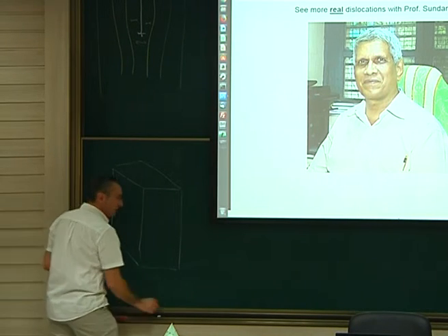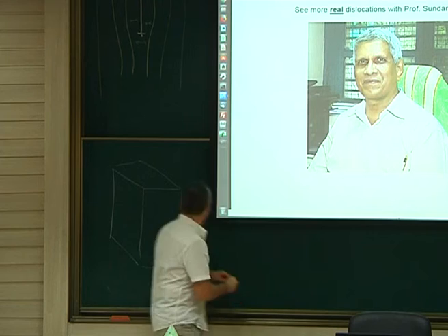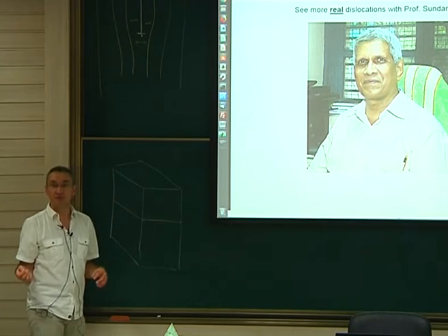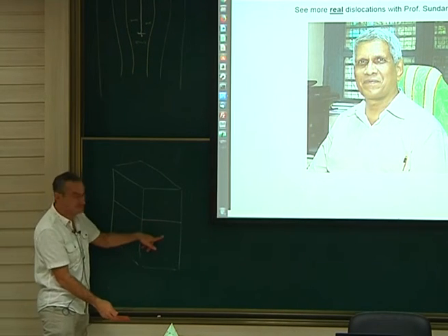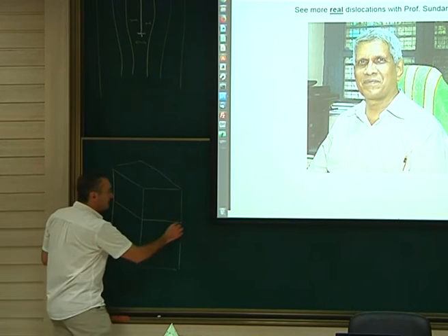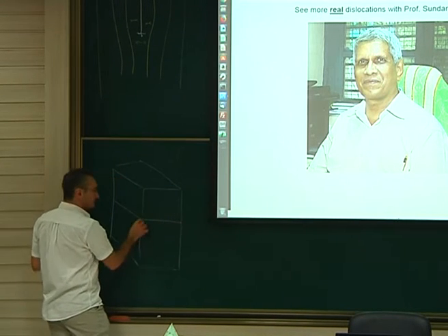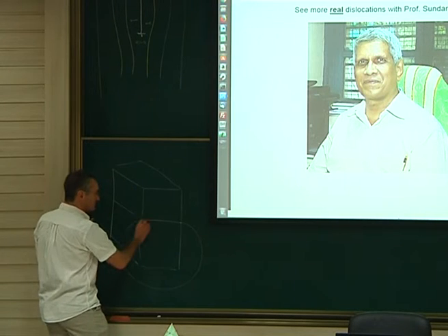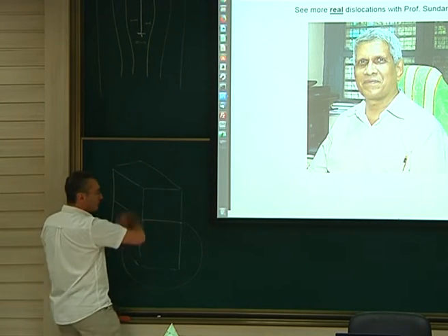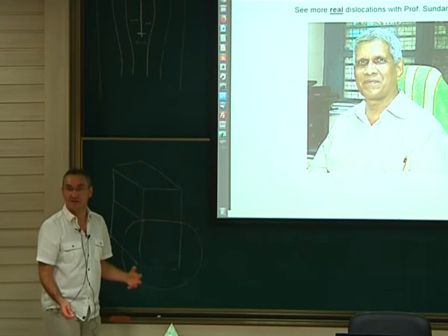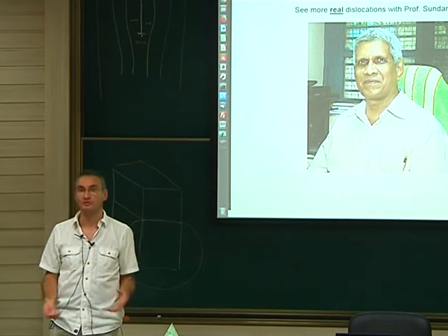So let's say that you have a loop which is shear. And you will do that with NuModis. If you apply a big shear on that system, and mostly zero shear on that system, then you will be able to bow out this segment a lot, so much that it can act like a Frank-Read source. So you may have a Frank-Read source in some part of the loop, which will make a huge plasticity, and that will accommodate anything you want, you see.